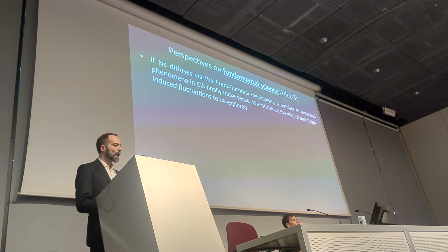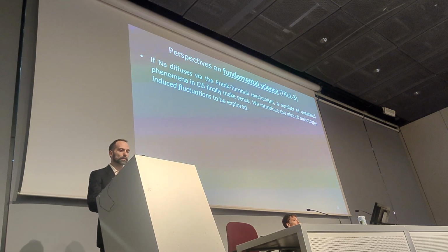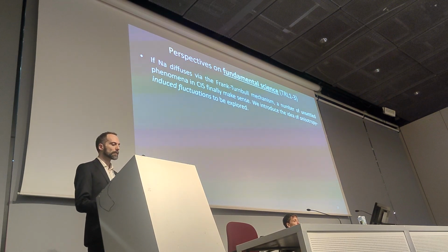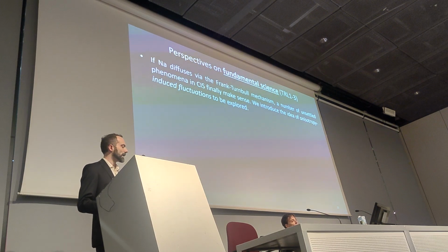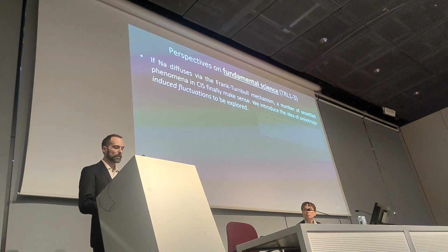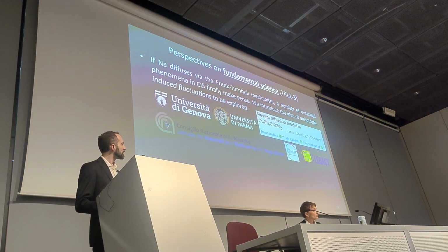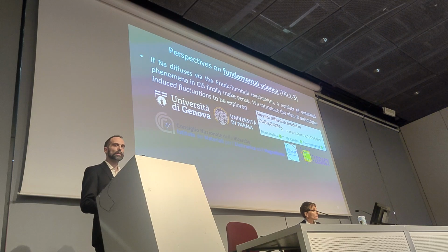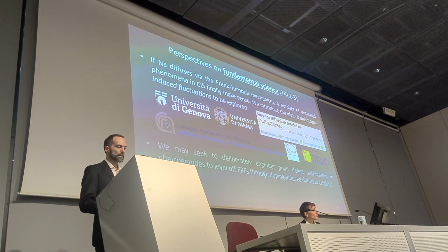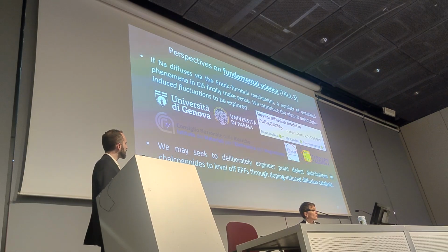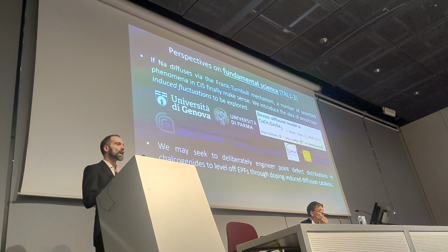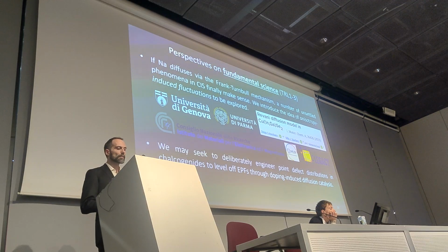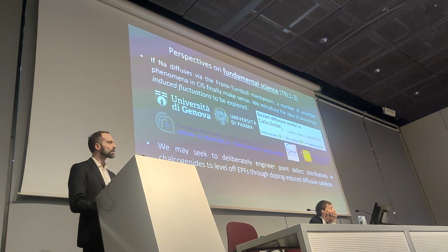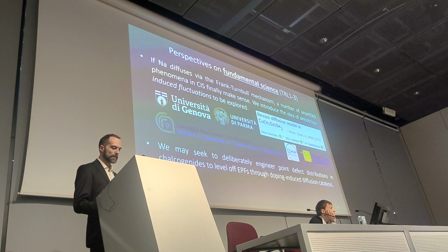Fundamental perspectives. If sodium truly diffuses through the Frank-Turnbull mechanism, a number of unsettled phenomena start to finally make sense. We introduce now the idea of anisotropy-induced fluctuations in CIGS to be further explored. If you are interested, you can read this recent paper, and we are working now on this national project together with the University of Parma and CNR in Parma to unravel these aspects. We may also seek to deliberately engineer point defects in chalcogenides in general, not just CIGS, to level off electrostatic potential fluctuations through doping-induced diffusion catalysis.